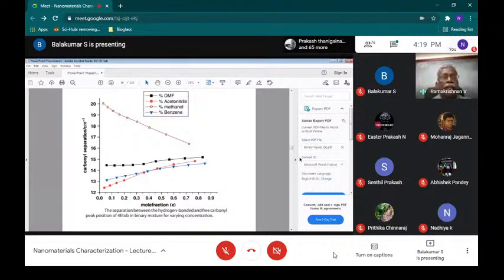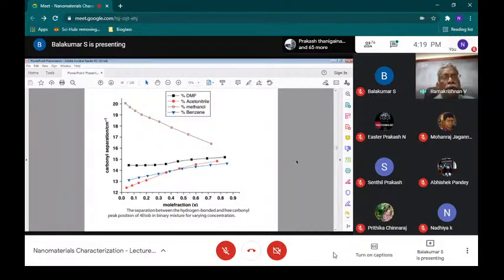So now you see that, okay, this is fine. Now you have a DMF; I put some stars here and there. Now the separation between the hydrogen bonded and free carbonyl position in binary mixtures for varying concentrations. At 0.7, that one particular concentration, you see that it shifted to 20, whereas in the other cases it has come down.